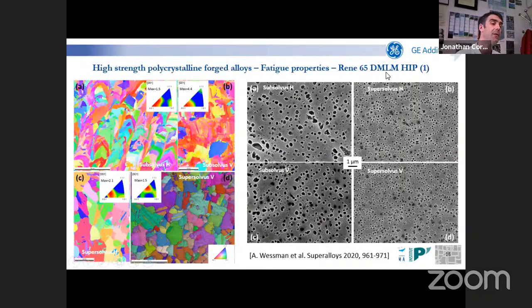And what we did, so this is a DMLM process, which is a powder bed fusion type process. And we have been studying the alloy along vertical, horizontal direction and using combined solution treatments plus HIP. So they are optimized processes to be able to get rid of porosity. We have typically less than 0.1% pores. I cannot give all the details on this. So what you can see in supersolvus treated state, we have microstructure very, very similar to a cast and wrought